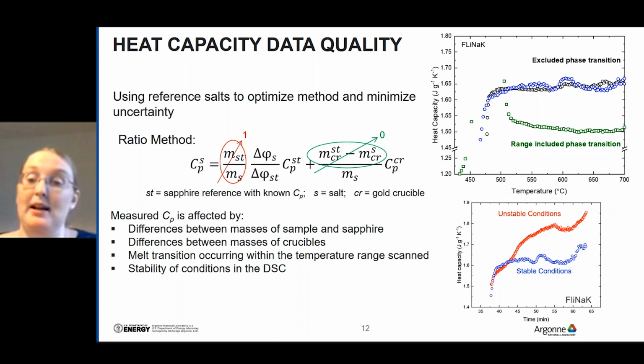We also discovered, as is illustrated in the bottom figure, that the stability of conditions in the DSC need to be closely monitored. Any instability at all can induce an artificial temperature dependence. You can see in the red data that there's a drastic positive temperature dependence, whereas when we ensure stable conditions in the DSC, we get a much flatter value.